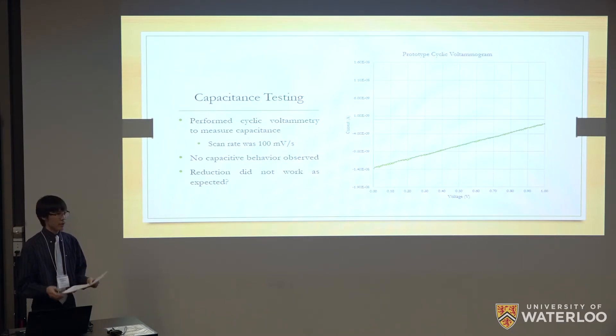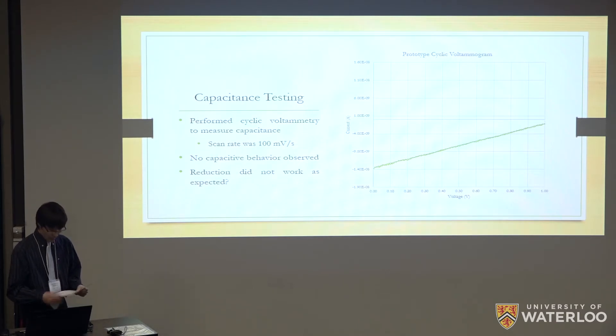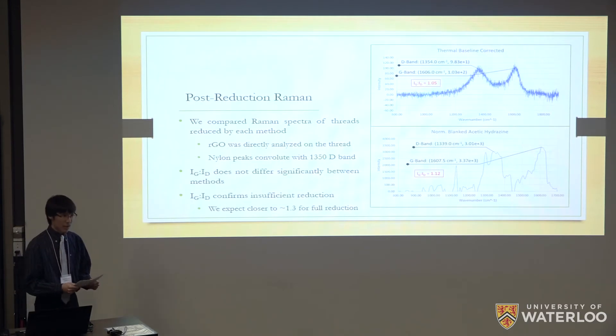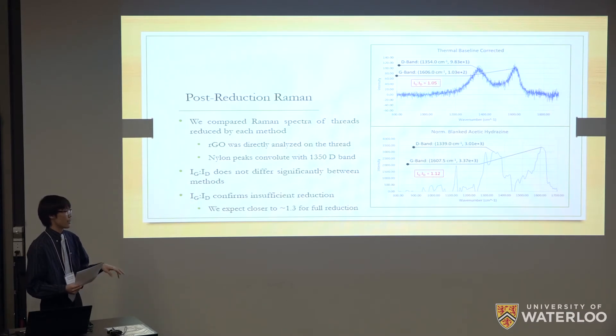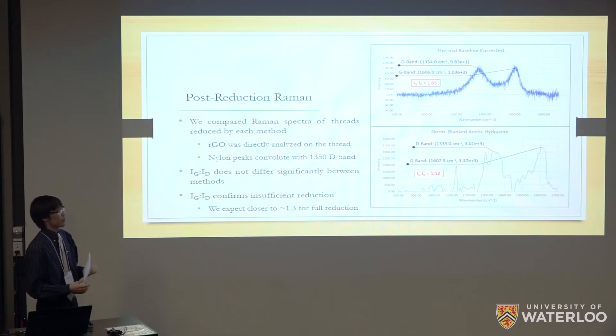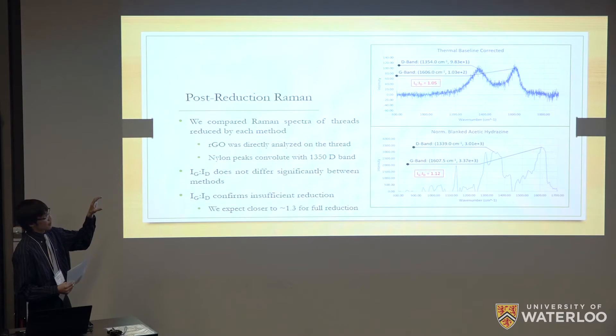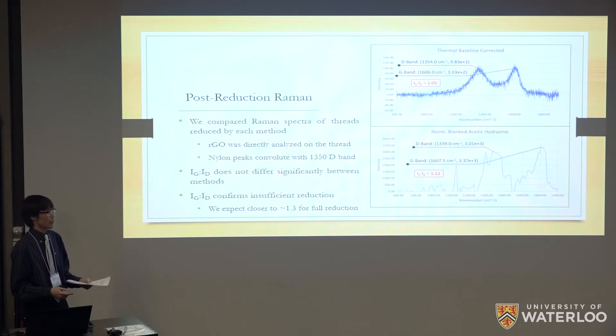We decided to look at the reduction method since we knew the conductivity was now working, so the issue had to do with either our electrolyte or our thread coating and reduction. We looked at the Raman spectra of the post-reduction threads. The graphs were noisier because we had to analyze the RGO samples directly on the nylon thread rather than on a PET substrate, and the nylon peaks convoluted with the 1350 D-band. We tried to baseline correct, normalize, and subtract that away, but it did result in some noise. From both reduction methods — thermal and hydrazine — they each reduced the thread to around the same extent. However, this was not the kind of reduction we expected. From literature, we were expecting a reduction ratio of around 1.3 to 1.5, so we now had a reason why our threads were not giving us enough capacitance even though they were slightly conductive.